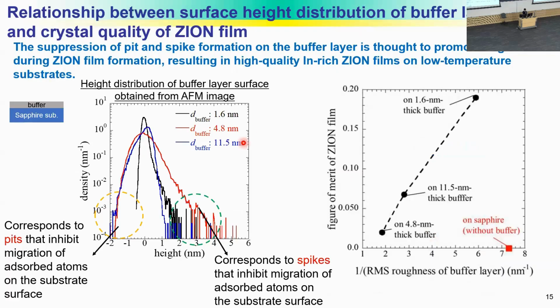Next, we show the surface height distribution obtained from the AFM image of the buffer layer. As shown in the left figure, the negative and positive parts of the height distribution correspond to pits and spikes on the substrate surface and buffer layer surface, respectively, which are thought to inhibit the migration of atoms. Therefore, the quality of the ZION films on the buffer layer with thickness of 4.8 and 11.5 nanometers is considered to be degraded due to the spreading of this surface height distribution.